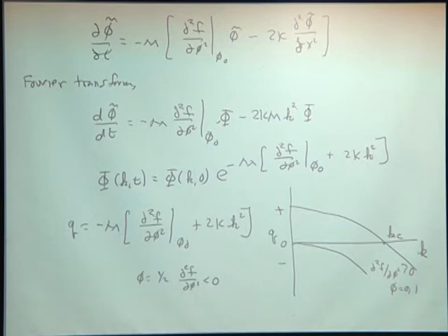In the Cahn-Hilliard case, you have to transport mass from one side to another in order to get this thing to work. So as the wavelength gets very big, that becomes a very long and difficult thing to do. It takes time. So the amplification rate of those waves as they go very, very long gets small.